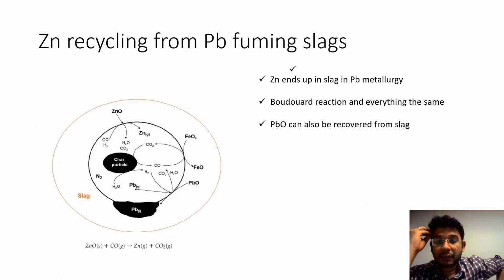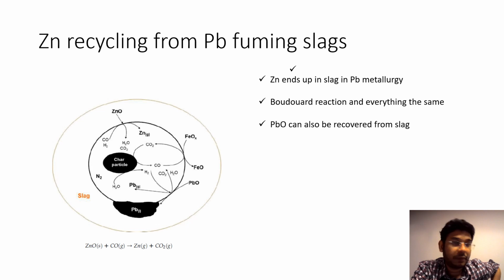So to end up, I will show two other sources. One is from lead slags generated in lead metallurgy, and another is an interesting source. The lead metallurgical slag is very simple. It's basically the same. Zinc ends up in slag in lead metallurgy because it's zinc oxide, and they try to keep conditions in such a way that lead forms as a metal and zinc goes into the slag as oxide. You take this oxide and put it inside a furnace, heat it up to 1200 degrees Celsius, and then you have the char together with the CO2, and then you have the Boudouard reaction, and everything is the same. You have the formation of zinc, and then the zinc vaporizes, gets oxidized, and goes into zinc oxide.